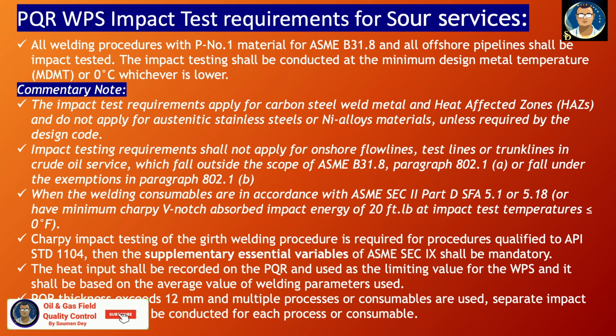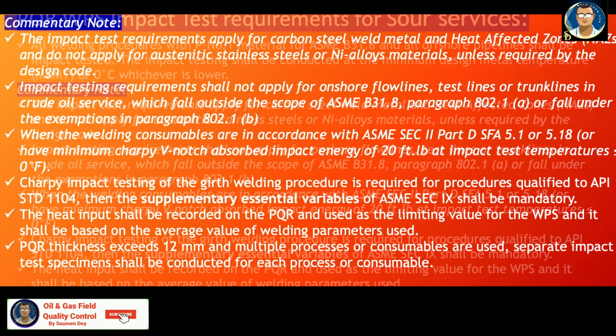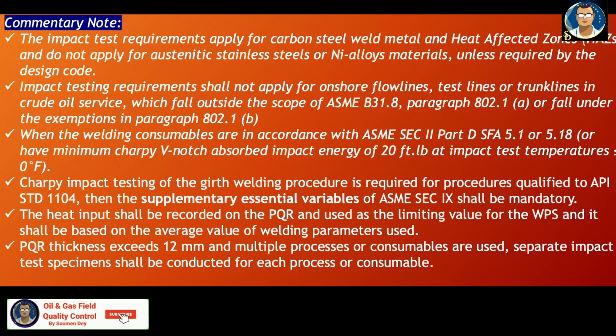All welding procedures for P number 1 material for ASME B31.8 and all offshore pipelines shall be impact tested, and impact testing shall be conducted at the minimum design metal temperature MDMT or 0 degree centigrade, whichever is lower. Some special notes: the impact test requirement applies for carbon steel weld and heat affected zone and does not apply to the austenitic stainless steel and nickel alloys unless required by the design code.